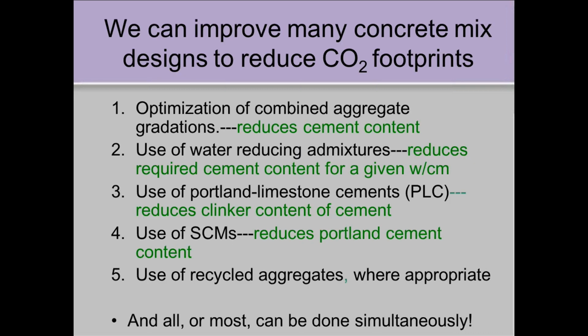Now I'll mention a couple of these things. We can do all these things at once. A lot of these things, they're not individual. There are individual things you can do, but you can usually do almost all of these things simultaneously, and we are doing them. You can reduce the cement content, as I mentioned, from combined aggregate gradations. Of course, water-reducing admixtures will allow you to use less water, therefore reducing the paste content of concrete, which allows you to get more aggregate in. The Portland limestone cements reduce the clinker content of cement. And the way we've designed these Portland limestone cements, they have equivalent performance to Portland cements, so you're not losing anything. It's fairly transparent to the users. And of course, we can use cement replacement materials such as fly ash and slag.